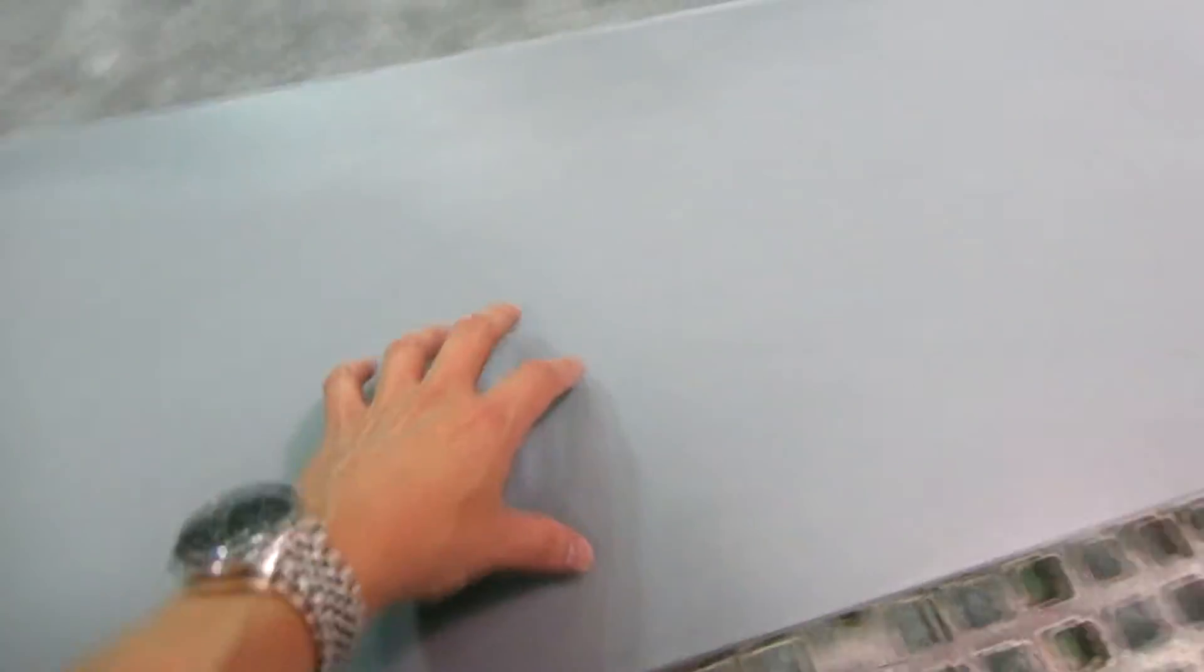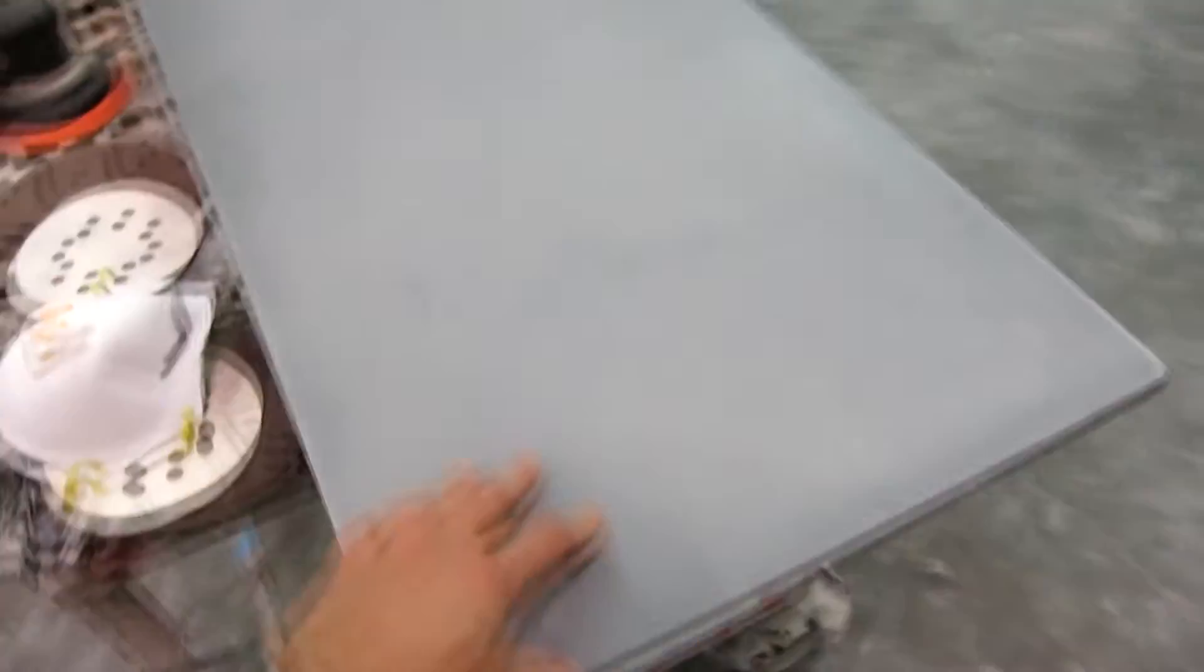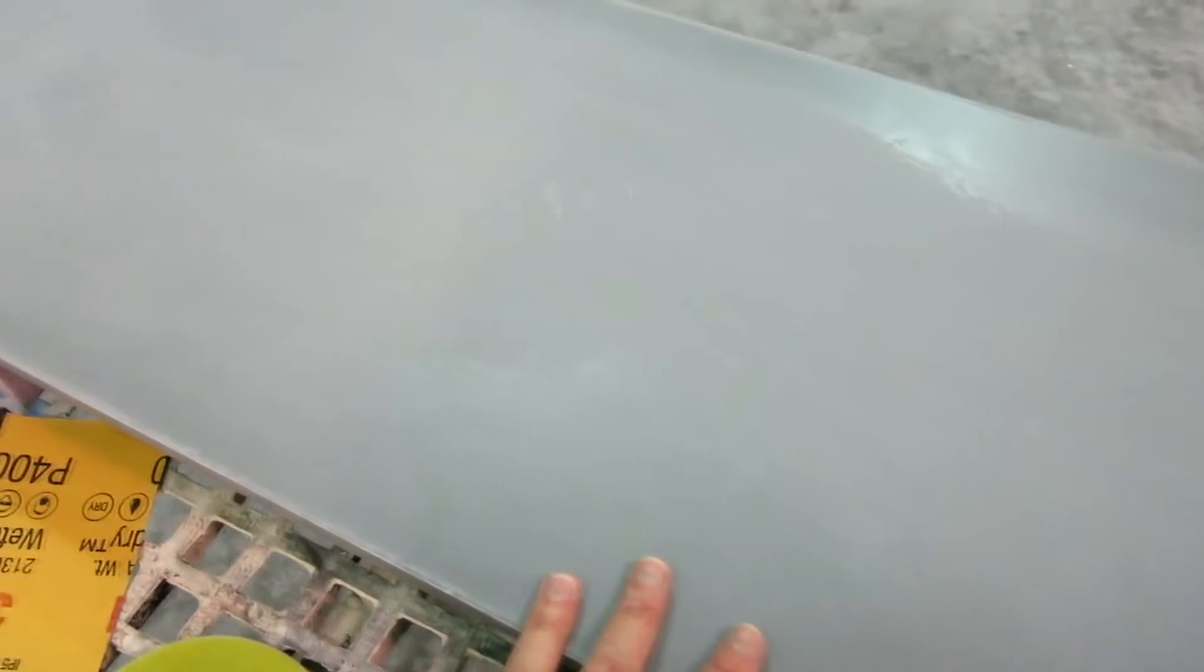Alright, so let's talk about the concrete I'm going to be showing you. This is four-day-old concrete. It happens to be Buddy Rhodes' ECC, cast at about a half an inch thick, at a water cement ratio 0.28. It's got a little color in it just to show the effects of the surface. It was left in the mold for two days and now it's on day four.